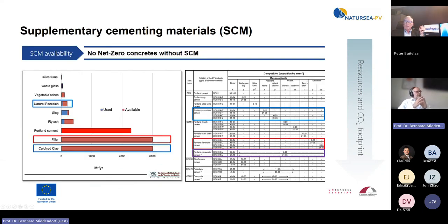When we look at what is available on the market, on the right side you see the SCMs' availability. We have silica fume. That was a question from one in the first talk. We have waste glass, vegetable ashes. We have natural pozzolans, a lot. Slag and fly ash we have to discuss. It is used and available, but the question is for how long. We have Portland cement, we can produce it, but we have a lot of fillers and we have calcined clay. So natural pozzolans and all others, we have enough, and then we can produce these cements with this. And then we have to use these cements for preparing UHPC.